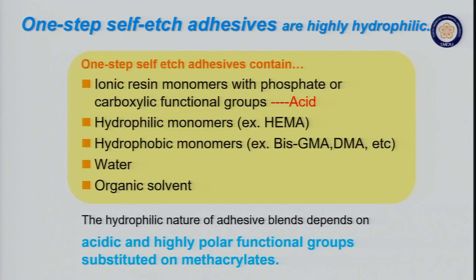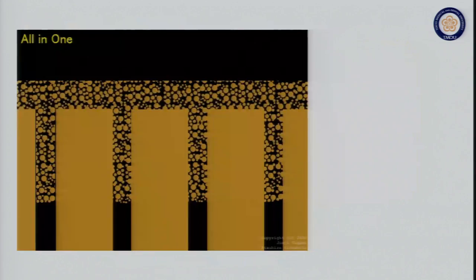Unfortunately, of course, this bonding resin can etch enamel and dentin, and it could penetrate into the surface layer. However, we cannot polymerize this water and solvent. That's why before you apply the light curing, these solvent and water should be removed from the interface. It is not so easy.